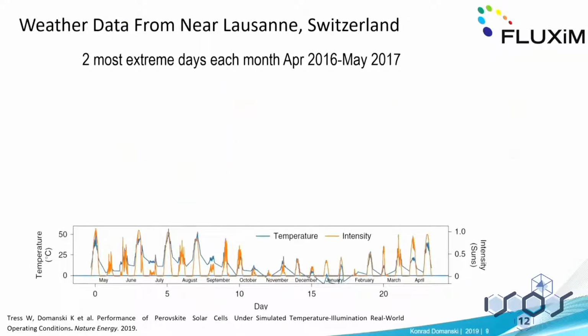So we did that pre-characterization to see how our devices behave across this parameter space. And now it was the time to subject them to some real temperature and illumination profiles. So what we did is we handpicked the two most extreme days in terms of illumination and temperature from each month between April 2016 and May 2017. This is how the profile looks, and we subjected both silicon heterojunction and perovskite cells, which were sitting inside the same sample holder, to those conditions.